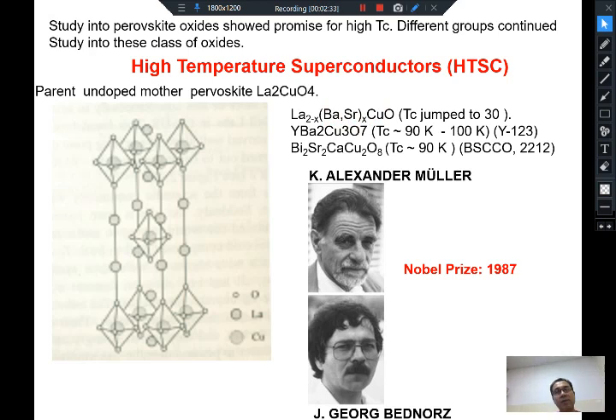and the moment you start doing that beyond a certain doping concentration, suddenly superconductivity emerges inside the material, and they found that the material becomes superconducting and the transition temperature at a certain level of doping peaked at 30 Kelvin. As you increase the doping concentration, the superconducting transition temperature keeps on increasing until it reaches a maximum. Beyond that concentration of doping, if you still keep on doping with say barium or strontium, then beyond that particular threshold limit, the TC again goes down. So there will be a dome-like feature. I'll come to that. But you see that Bednorz and Müller, by taking this parent antiferromagnetic insulator of lanthanum copper oxide and by doping it, just merely by doping it, they suddenly discovered a very high transition temperature.